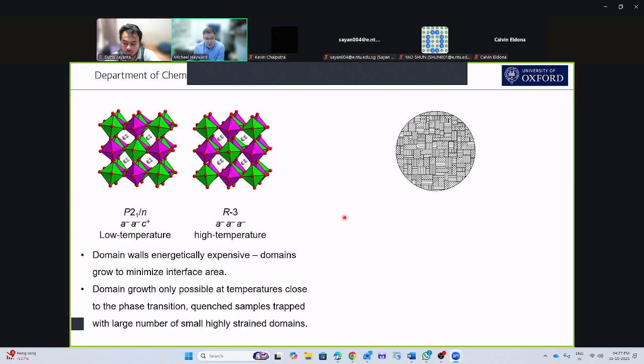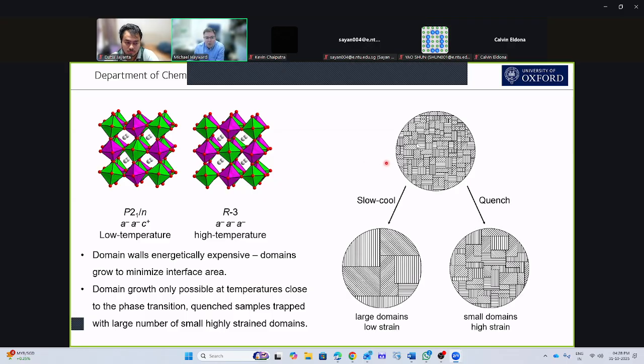So the system will try and convert to a single domain of one orientation. However, that conversion process, that reorienting of the direction of the domain, is very expensive. It has a high activation barrier. And so we can only do that reorientation at temperatures close to the transition temperature. So if we slow cool a sample, we spend a long time in that temperature region and we can reorient a large number of the domains.